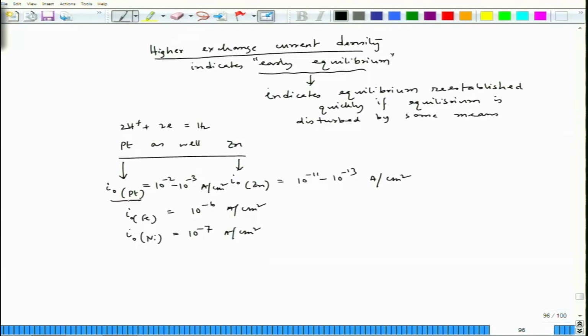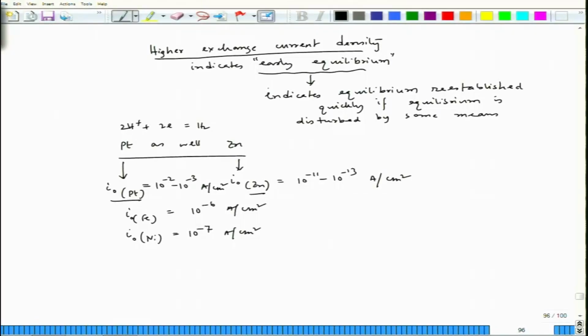That means, on platinum surface, hydrogen reaction would achieve equilibrium quickly compared to zinc surface. It will take much longer time on zinc, and that means if we make some standard reduction cell by using zinc, it will not be a good practice, because it will take long time to establish equilibrium, and then if somehow equilibrium is disturbed, it will also take long time to re-establish that equilibrium. So, that is why platinum is very much the preferred electrode for the standard hydrogen electrode.